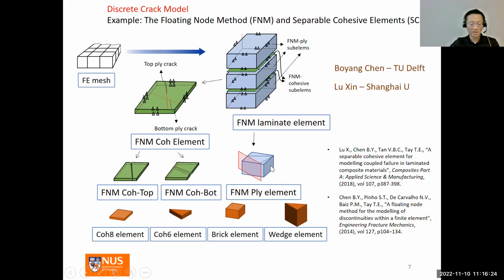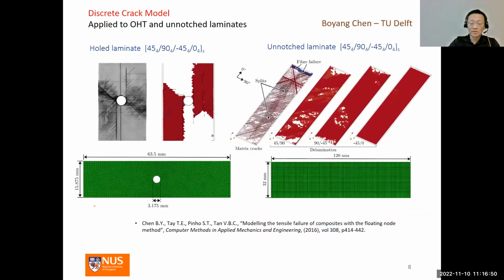Separable cohesive elements are inserted in between plies for modeling possible delamination. The partitioning of the brick and cohesive elements must be made compatible to enable correct interaction between matrix cracks and delamination. This is particularly important for delamination migration between the interfaces. The floating node method was successfully used to model cracks and damage in both notched and unnotched laminates. So here, the delamination is indicated by the red-colored areas as modeled by cohesive elements, while the matrix cracks are modeled by partitioning the brick elements in the plies.